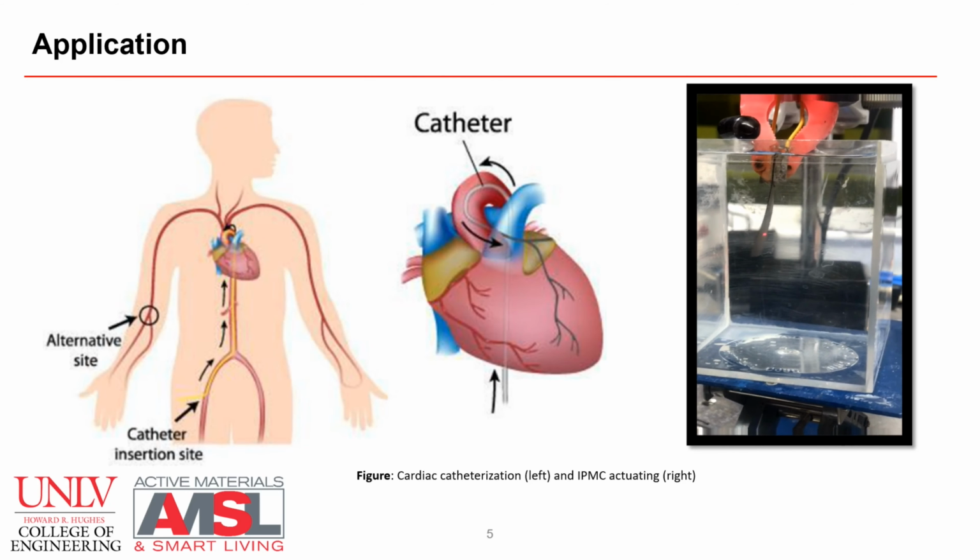Therefore, understanding the effect of temperature on IPMC is important in the prediction of the electrochemical behavior under different environmental conditions. Increasing temperature will expand Nafion's nanochannels and increase the kinetic energy of the clusters. Benziger's paper talked about how the elastic modulus of Nafion decreased with increasing temperature. The free volume increases with increasing temperature as the nanochannel expands.